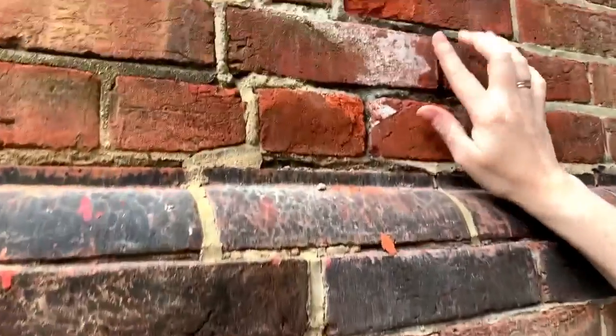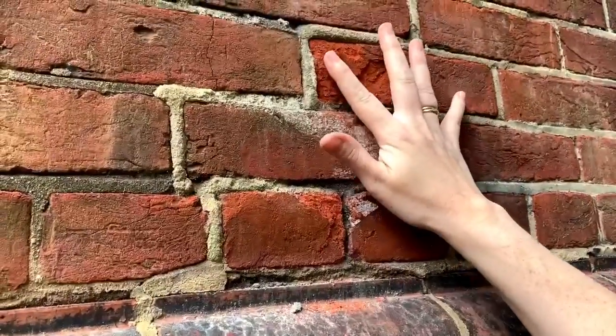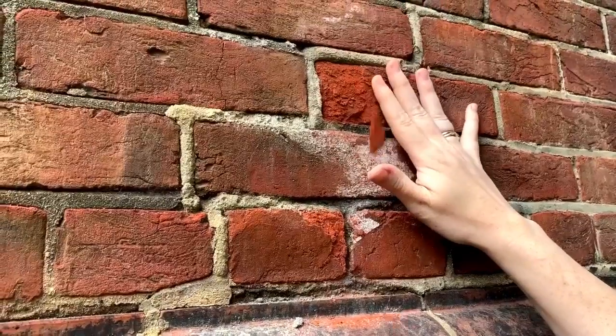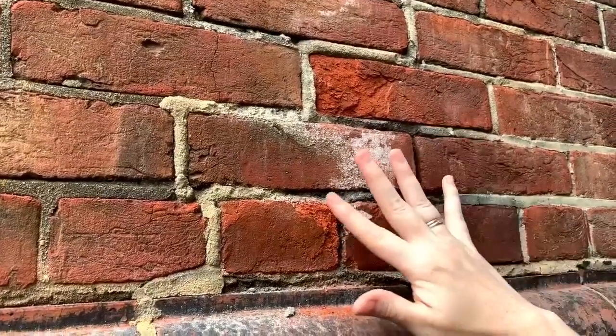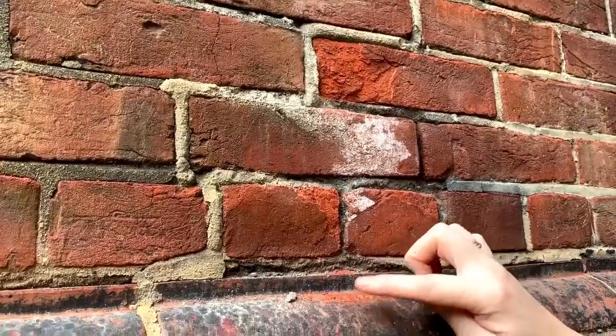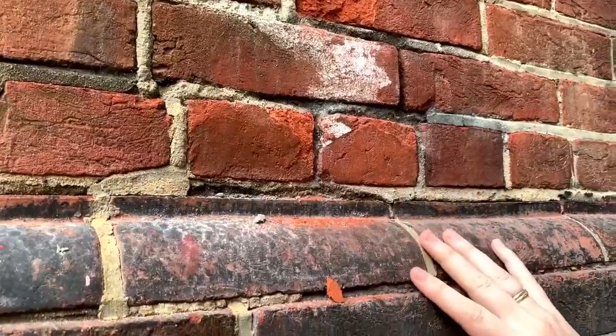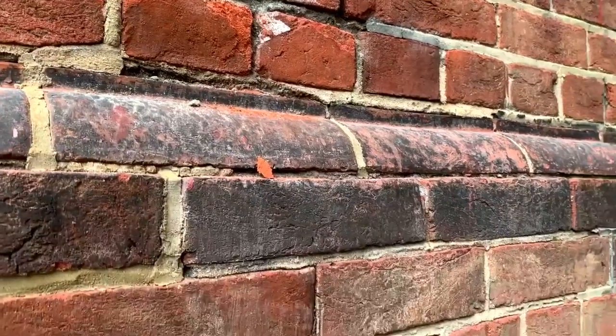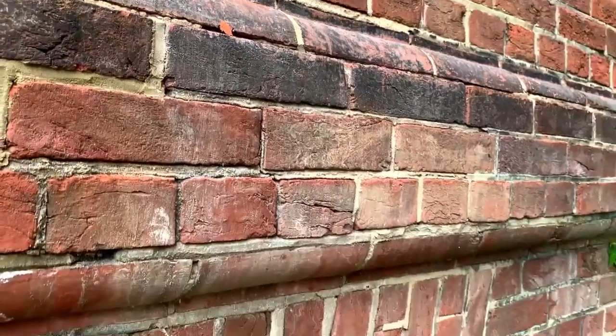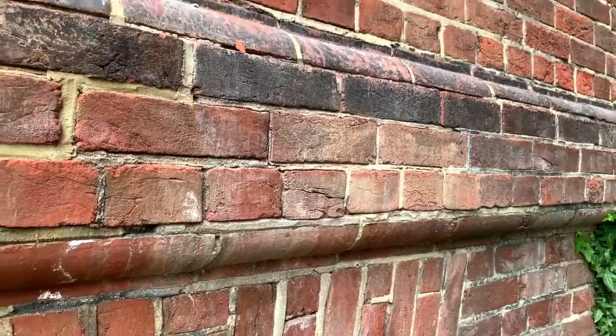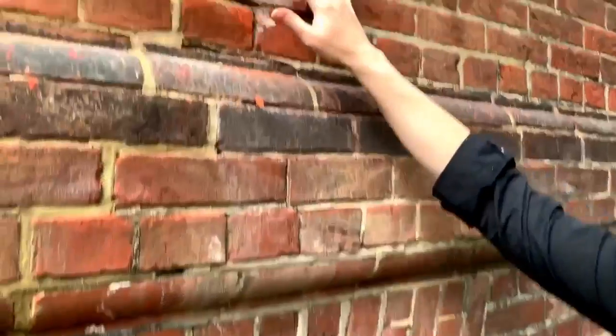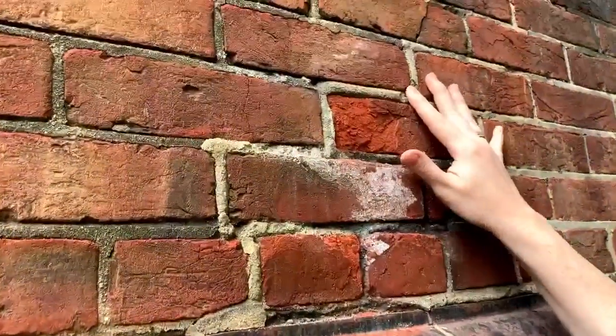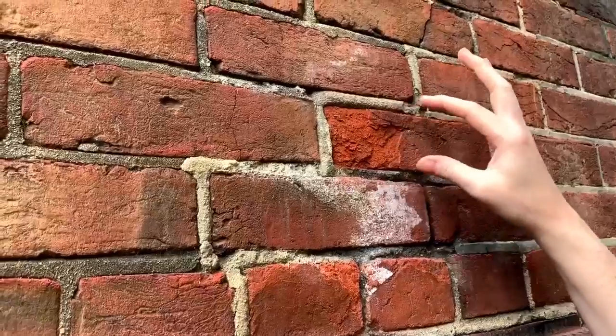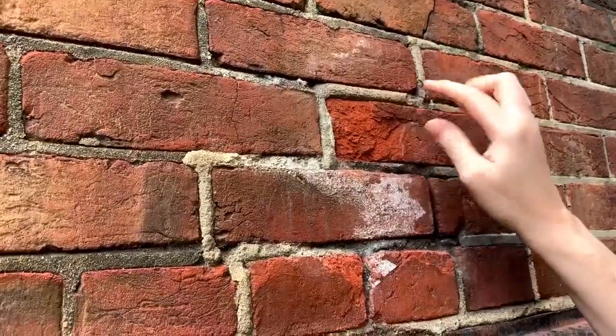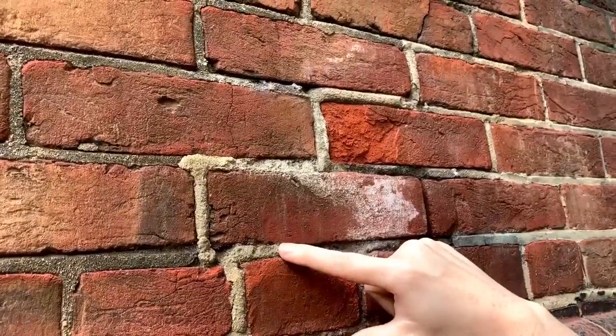Efflorescence up here specifically will start doing things like this, where the entire fired skin of the brick starts to simply fall off. You get brick dust around the edge of your building, right where that has essentially turned back into sand. We know that the hardness of the mortar is the culprit because we're literally only seeing it on the bricks that are surrounded by this specific repair.